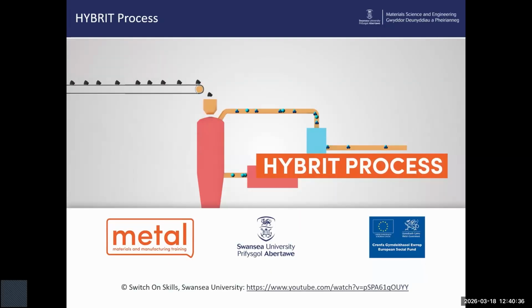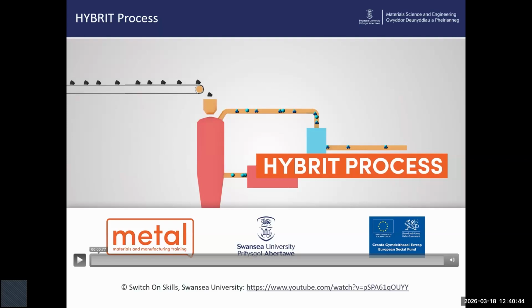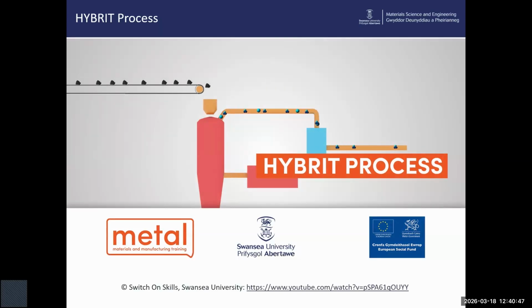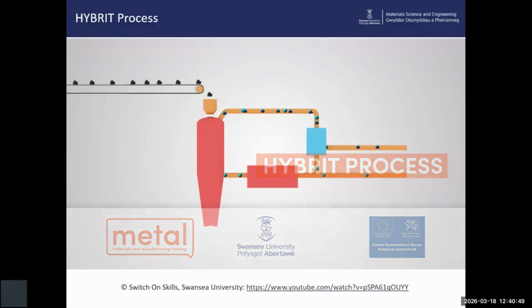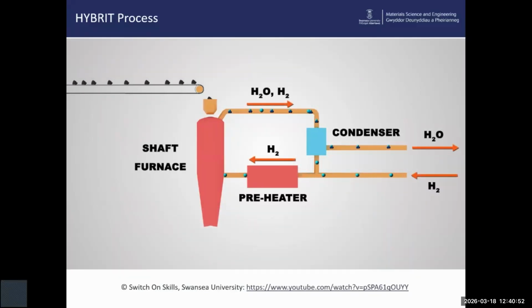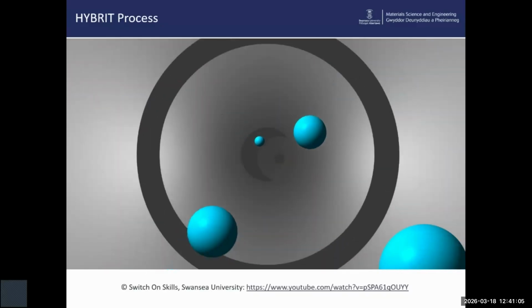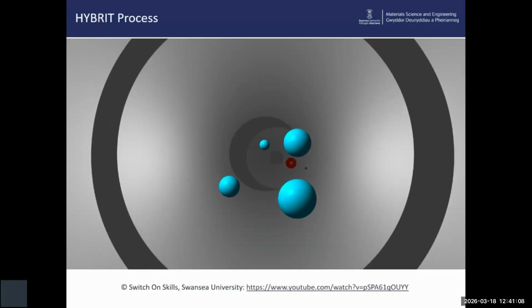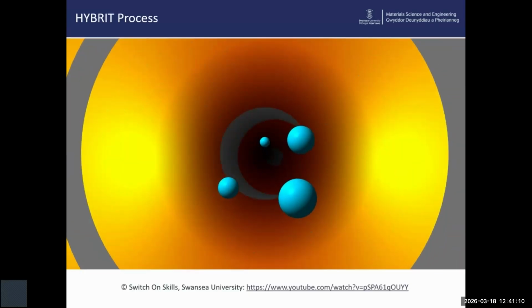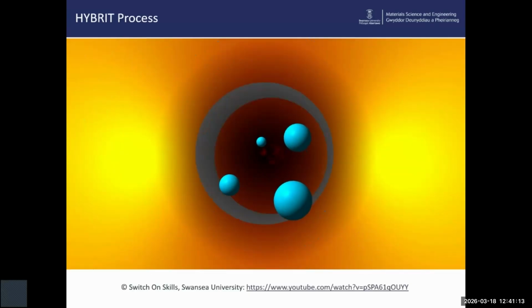Last video, and it's only 1 minute, I think, showing how hydrogen can be used in the steel making process, in the process called the HYBRIT process. The HYBRIT process is considered the most promising for iron ore reduction to metallic iron by hydrogen. Iron ore pellets or lumps in the form of hematite, Fe2O3, is fed into the top of the shaft furnace. Hydrogen is heated to between 800 and 900 degrees centigrade and blown in from mid-furnace.